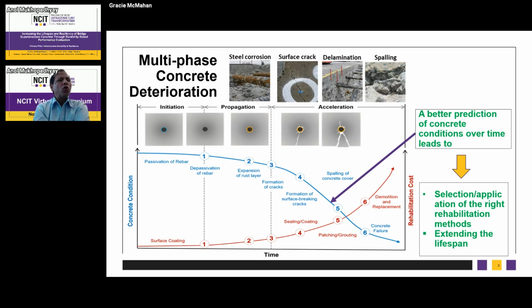One is the live load as well as the environmental, which is primarily corrosion of the concrete. And you see the concrete corrode, and it ultimately leads to crack development, delamination, and failure. So if we have a better prediction of the concrete conditions over time, then we can make a better decision for the right selection of rehabilitation methods, extend the lifespan and save the repair costs.